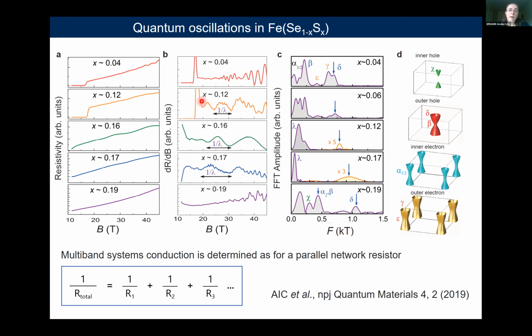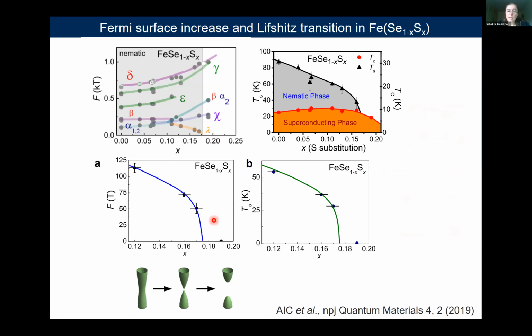This effect was somehow unusual because in ARPES we know that the small three-dimensional pocket is supposed to be there, but it is not supposed to go away, because it's found also for 18%. So it's almost as if there is another transition happening exactly at the nematic endpoint, which could have a different origin from what we see in ARPES. And so we think that this is potentially a Lifshitz transition, where you can think that one of the cylinders becomes extremely distorted by chemical pressure, so the warping increases, and at some point it loses the center of this band and the orbit is gone.